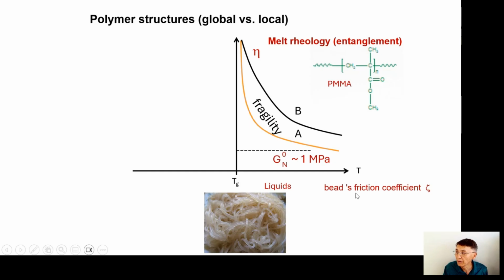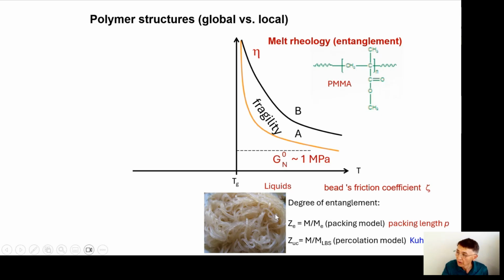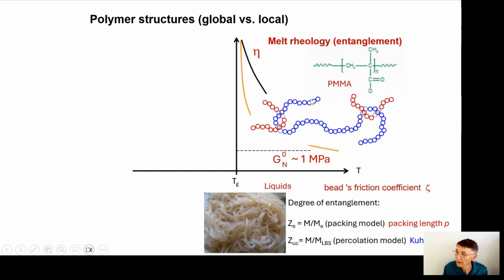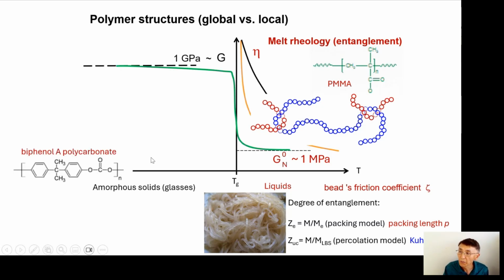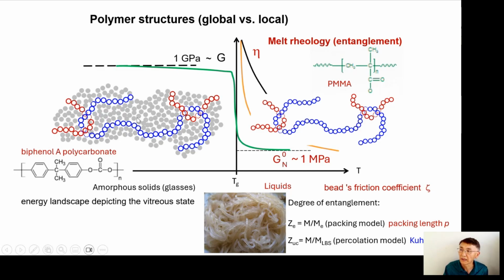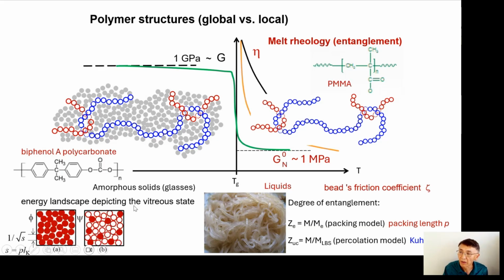Well, the structure you have from rheology, we know it's like a ball of spaghetti, and we can characterize how long the chains are, which can affect the viscosity of it, the solid behavior. The degree of so-called entanglement can be defined in different ways. To us, it seems important that the entanglement arises from this uncrossability, which is preserved when you go to the glassy state. It's still there, that entanglement, that uncrossability. So through rheology, we learned also about the solid structure, which is a matter of acknowledging that there is this underlying polymer network.